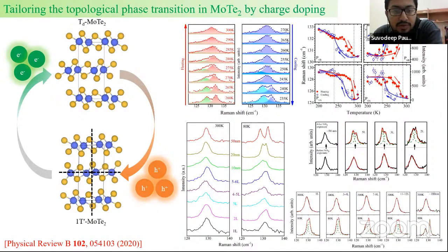But ma'am, I would clarify a bit. For bulk, it's at 250 Kelvin, but the phase transition temperature has a thickness dependence. So for a thinner flake, we expect it at lower temperatures. And I just wanted to know, whenever you are going to the Td prime phase, do you have any signature of this negative phonon, or any signature of structural instability in the system? Because I am doing calculations presently on this system. That's why I'm asking the experimentalists.